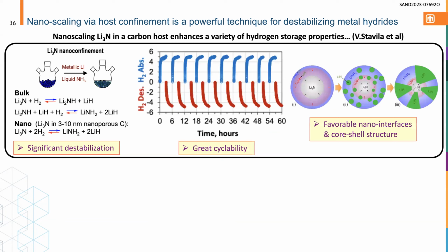So one thing that Sandia and Mark and Vitaly have been working on for quite a while, even well before I joined Sandia, is nanoscaling of metal hydrides in nanoporous hosts. So if you click, Rob, one particularly interesting example of this is confining lithium nitride in a nanoporous host. So you get a lot of benefits from doing this, which we don't have time to discuss, but you significantly destabilize the reaction. So that's great. Lithium nitride typically hydrogenates with a delta H on the order of 70, which is way too high. And you get it all the way down to the 40s by doing this nanoscaling.